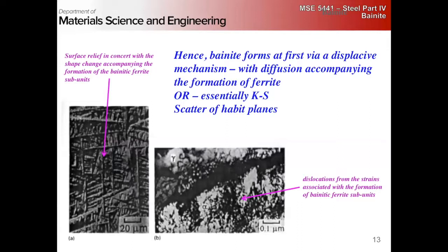Well, you go from austenite to a supersaturated ferrite. How supersaturated it is depends on what mechanism you ascribe, whether it's diffusional or diffusionless. If it's, let's just say it's diffusionless, you have a shear transformation that goes from austenite to supersaturated ferrite, then diffusion of the carbon out of the supersaturated ferrite to form cementite at the interface, right?